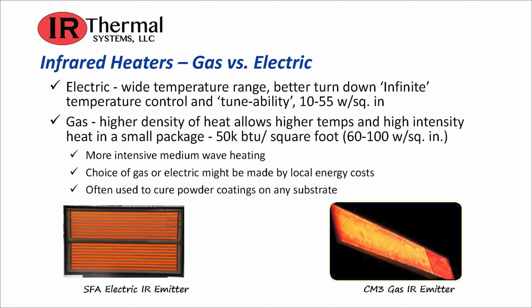So the electric heaters have a wide temperature range with better turn down, with infinite temperature control and tunability. They're specified in a range of 10 to 55 watts per square inch. Gas infrared heaters, the difference is that there's a higher density of heat that allows higher temperatures and high intensity heat in a small package. That's up to 50K BTU per square foot or 60 to 100 watts per square inch. So as I said, more intensive medium wave heating. The choice of gas or electric might be made by local energy costs. A lot of times, your local energy costs and the comparison will decide what you're going to do in that plant. And they're often used to cure powder coatings on any substrate.